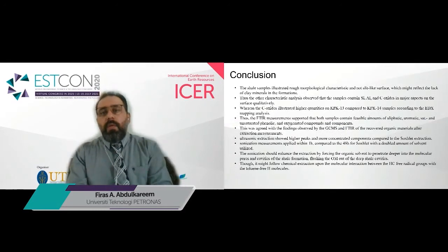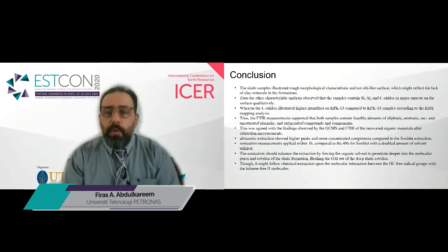So from that, we can conclude that the ultrasonic assisted process to extract the heavy hydrocarbons and organic matter is considered more feasible and more economic, according to the time that we need, a few minutes, or even 1 hour, compared to the 48 hours. And the amount of solvent needed is almost half, with a wide range of hydrocarbons extracted, and a higher percentage and amount of organic matter extracted than the traditional way, which maybe needs further analysis and studies on some pilot plants and some practical amounts of shell, to finalize feasible outcomes and applications.